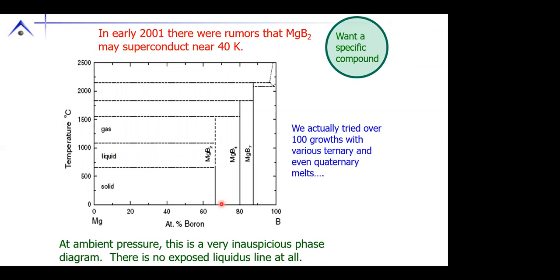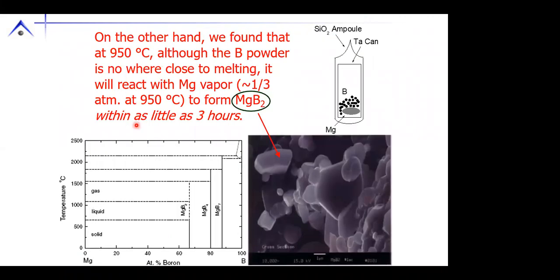Now, despite hundreds of growths of binary, ternary, quaternary, it is not simple to grow single crystals of MgB2 at ambient pressure. You can go up to several gigapascals and get them, but that was later. On the other hand, as physicists interested in the science of superconductivity in this material, we'll measure what we can. So we devised a way of growing high purity polycrystalline samples.